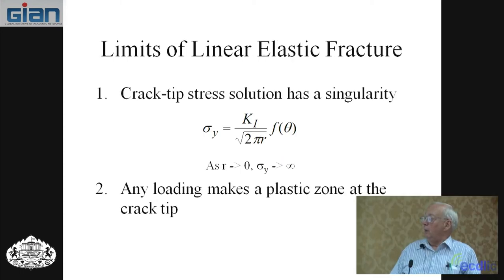First thing, look at the crack tip stress, and you see this, 1 over square root of r, and r, remember, is the distance from the crack tip to the stress element. So as the stress element gets closer and closer to the crack tip, you get what's called a singularity, 1 over square root of r singularity. So as r gets close to zero, the stress goes to infinity. Now you would think that infinite stress then should cause failure, but that's not necessarily so.